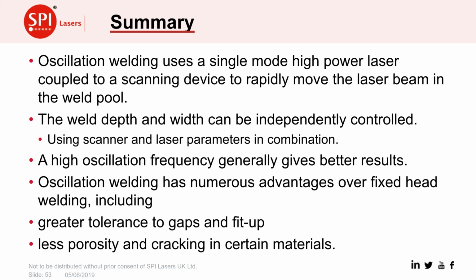And just a couple, again, to highlight other areas of advantages for oscillation welding. We've got this much greater tolerance to gaps and fit up than we would get from a normal situation, such that we can use it to tackle welding applications where a normal fixed magnification weld head just wouldn't be able to provide the range that's needed to cover the gap and still give you the power density you need for a good weld. And because of this control over the weld pool, that we're running it around and allowing it to cool more slowly, we can get much less porosity and cracking in those materials which tend to be sensitive to that.